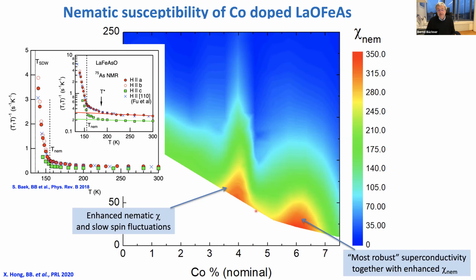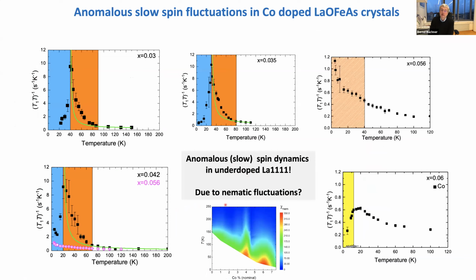And of course, this means that we have a very interesting region here. We have these very slow nematic fluctuations, which are coupled to the spins, and somehow this should also show up in unusual spin behavior. And that's also what we see. What I've plotted here is also measured on these single crystals: the NMR relaxation rate on compounds where you still have the magnetic order. You see the strong peak, and then this magnetic order disappears, and then you observe a very unusual behavior of 1 over T1T.